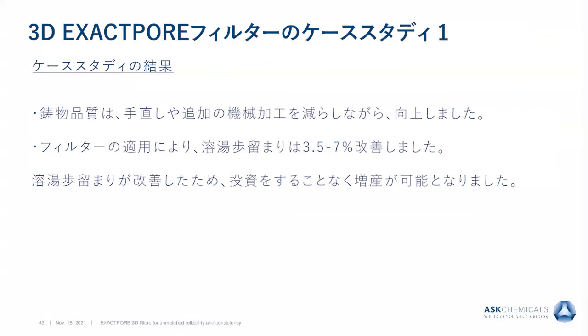The final results at this customer: the casting quality was increased, lowering the need for rework and additional machining, while yields were improved 3.5 to 7% depending on the filter application or orientation. Due to these increased yields, production increases were realized without any additional capital investment.